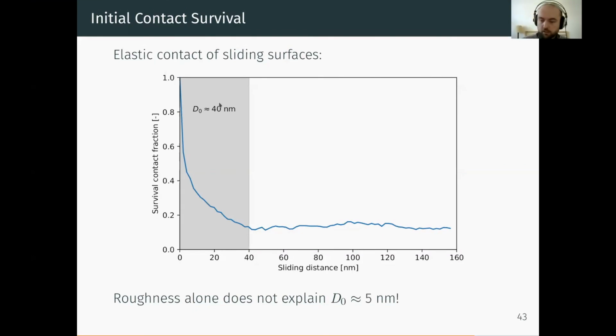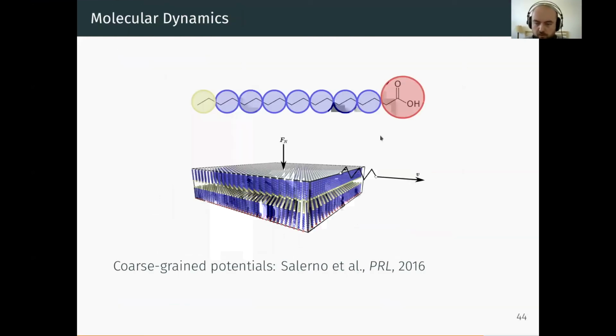So in order to get as close to the experiment as possible, I set up a molecular model for the fatty acid molecules that they use in the experiments. What I did was to use coarse-grained potentials, which allow me to save a bit on computational power, because each bead here is 2 CH2 groups. I set up a surface of those fatty acid molecules for the top and bottom surfaces, because we know that the friction interaction is going to emerge from the interaction between the tails of those molecules. I press with a normal force on this system, and I pull with a spring at a given velocity.